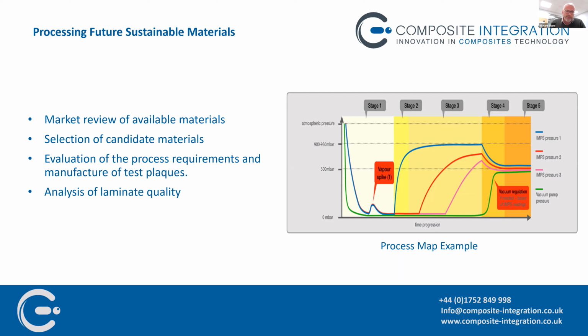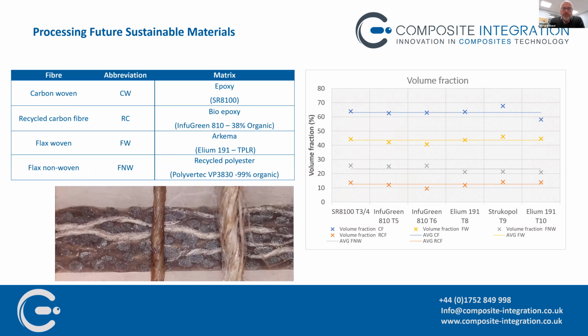So we were particularly interested to start looking at some of these materials in depth and actually work out whether the quality of the finished component was acceptable and how easy they were to process in a liquid resin environment. So a few of those materials, we surveyed the market pretty heavily, and we picked just a few to start with. On the fibre side, we took woven carbon as a reference material and a pretty standard epoxy as a reference material. We're then looking at recycled carbon, woven flaxes, non-woven flaxes. And they've all been around for a while now and are probably familiar to many of you.